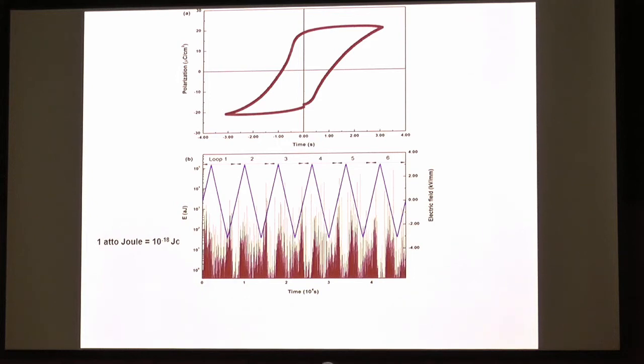So here we have the measured hysteresis, polarization against time. You put an electric field in with a constant speed, and you measure the polarization. While the polarization is measured, you measure also the jerks which are seen or heard by the microphone. And what we do is we measure extremely slowly. Each time, from here to here is one hysteresis. So we measure 6 hysteresis overnight. And then we have to analyze the jerks here.